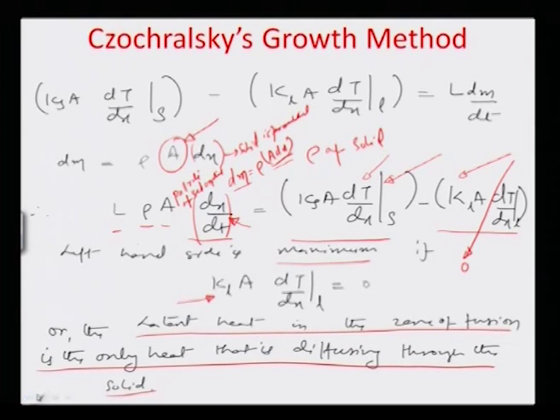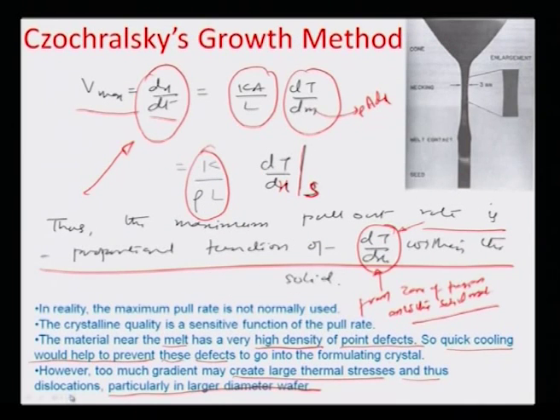So it is really a trade off between the pull rate and the way the defects would go into forming the crystals, or the amount of thermal stress that the crystals can handle, and together this defines how much pull rate is really needed. Sometimes it is not a yield based decision. It is based on the purity of the material, particularly because we are growing single crystalline silicon here, purity in terms of point defect density, and also thermal stress created dislocations, etc. So it is a function of a lot of other quality parameters for the wafer apart from the yield. So that is how the Czochralski growth process works.